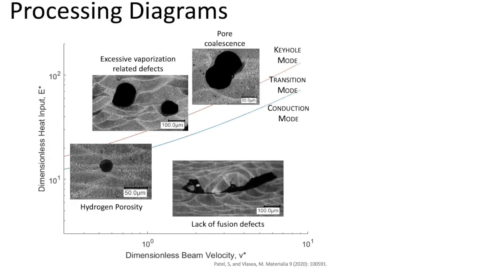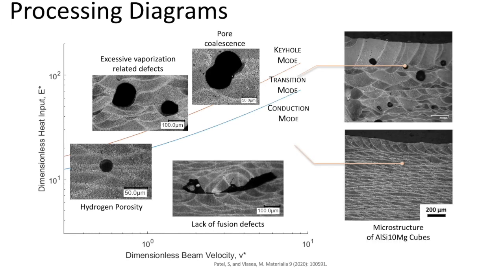The processing maps help us analyze the physical origins of a given defect and guide us quickly towards a set of ideal processing parameters for a given alloy. This work has previously guided us towards the use of defocused laser beams for AL-SI10MG, leading to a uniform conduction mode microstructure. We used our prior knowledge with this alloy as a starting point for generating a process map for Scalmalloy.